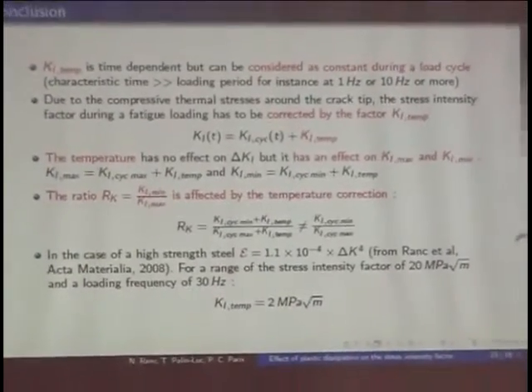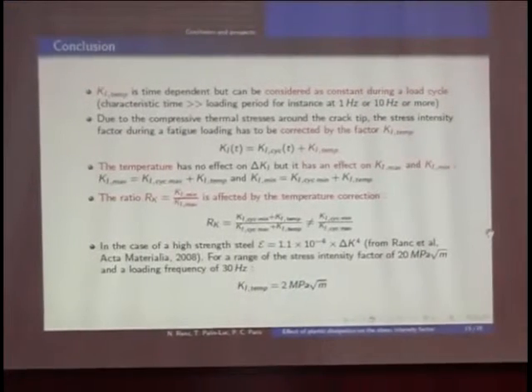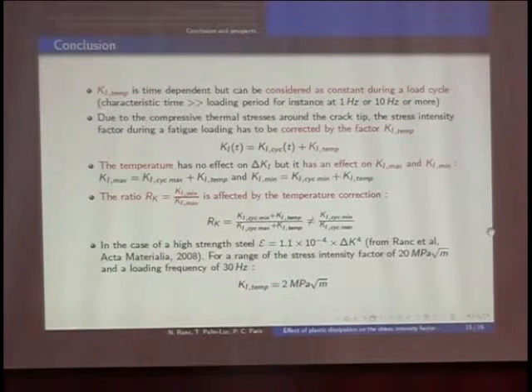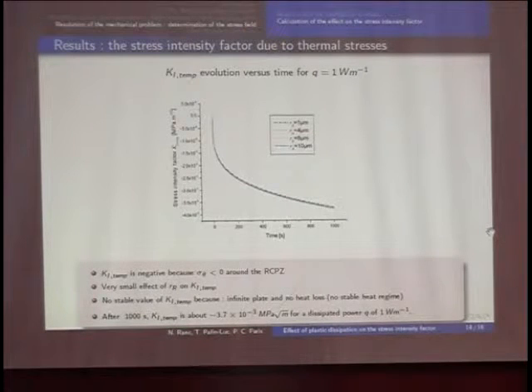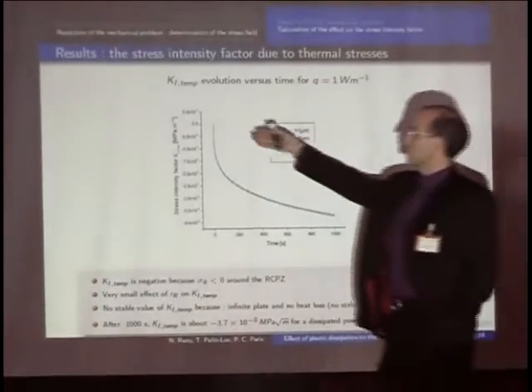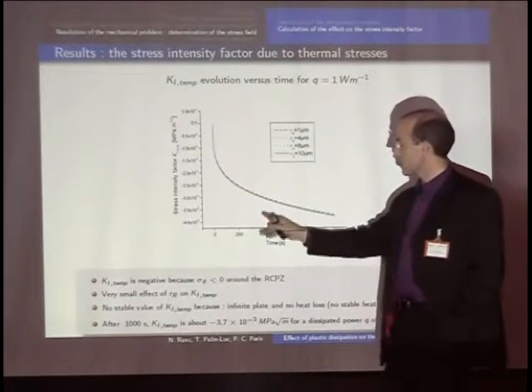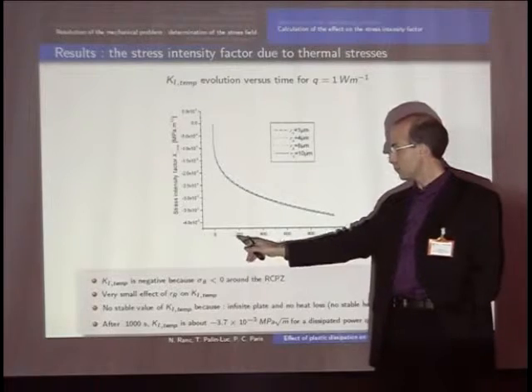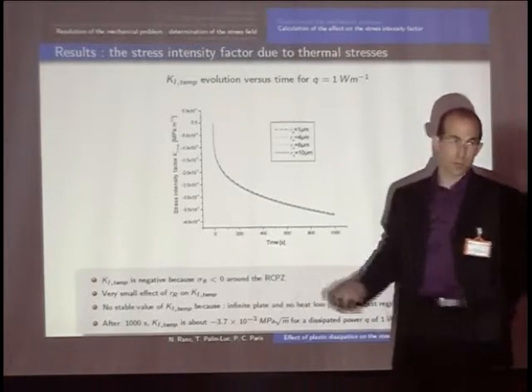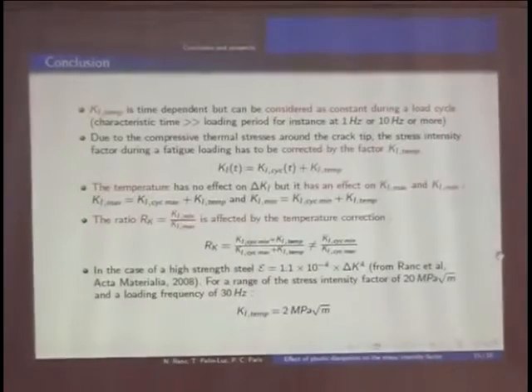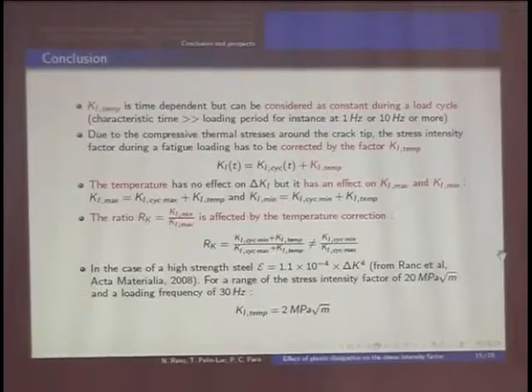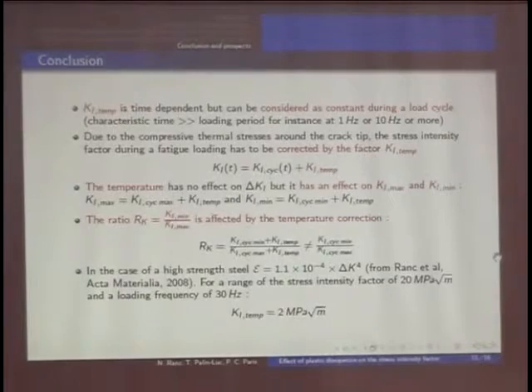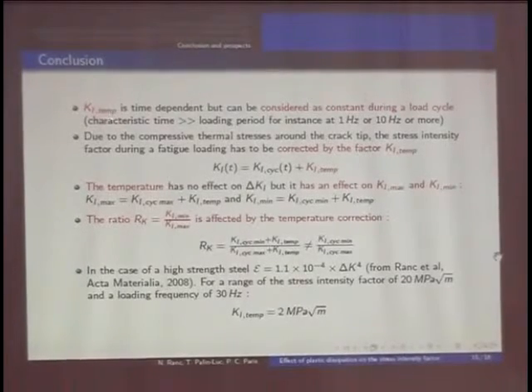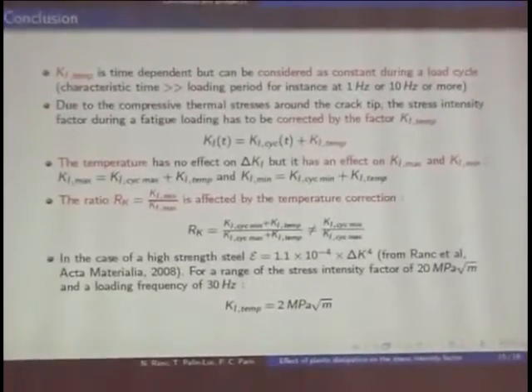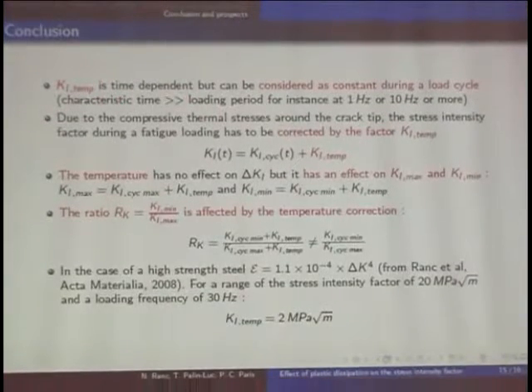So, in conclusion, we can say that the temperature effect on the stress intensity factor in mode 1 is time dependent. But if you come back to the curve, after the beginning of the cyclic loading, we can see that the characteristic time here is 200, 400 seconds. If you compare to a cyclic loading at 1 Hz or 10 Hz, we can consider that during one cycle, the effect on temperature is negligible, because the characteristic time of heat conduction is very big compared to the loading